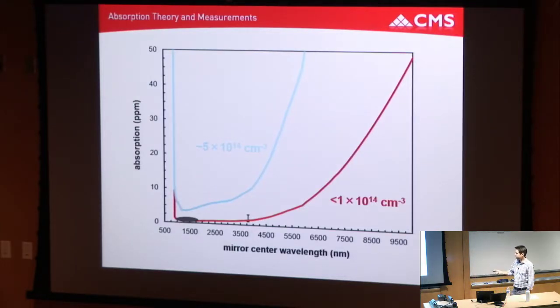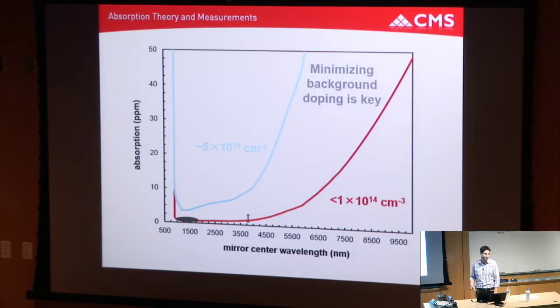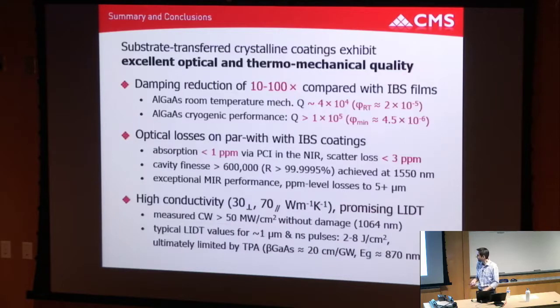And here's going back to that theoretical curve. This is two different doping levels, 5 times 10 to the 14 n-type and less than 1 times 10 to the 14. We don't reliably get this. The problem is from the foundries, we can't control what was grown before, and the systems inherently have dopants in them. But on good runs, we can push down to this sub-1 ppm in the near IR, and we've shown down to single-digit ppm out to 3.8 microns. And really minimizing background doping is the key. You want an MBE system with no dopants, just gallium, aluminum, and arsenic.